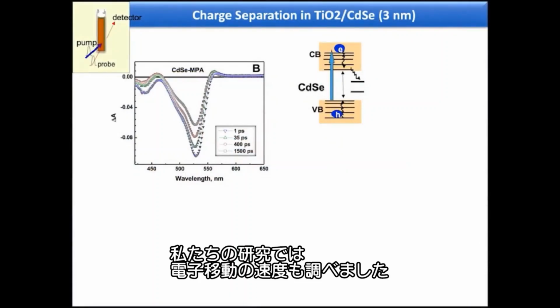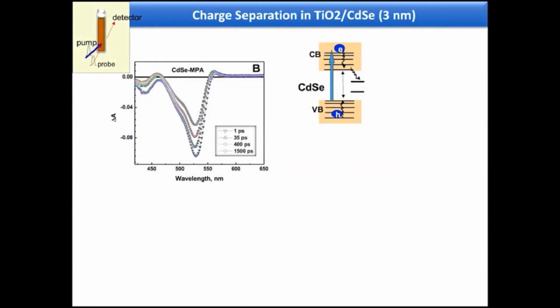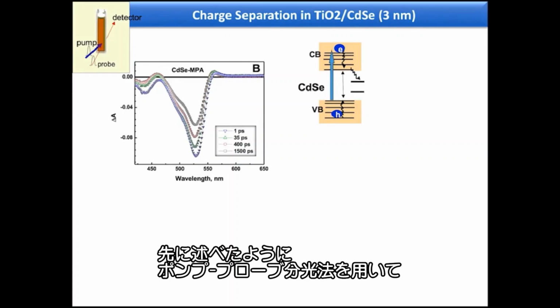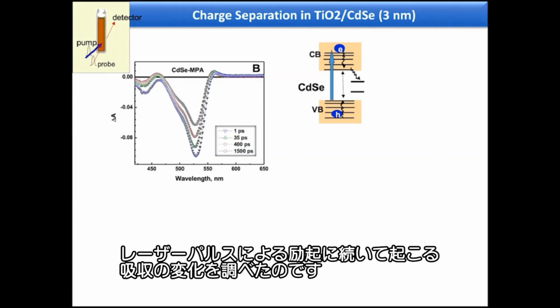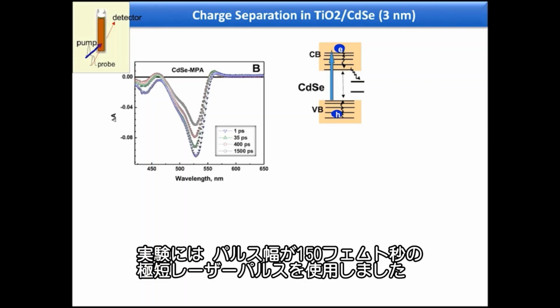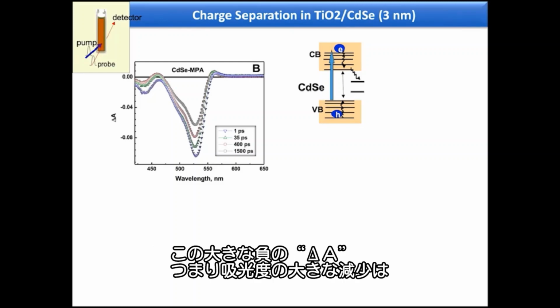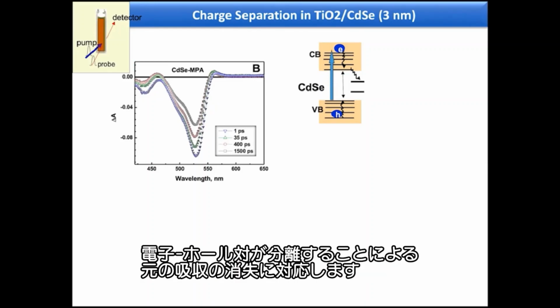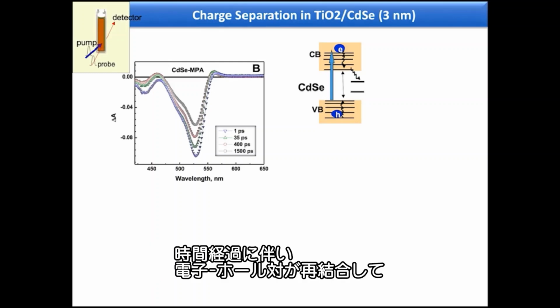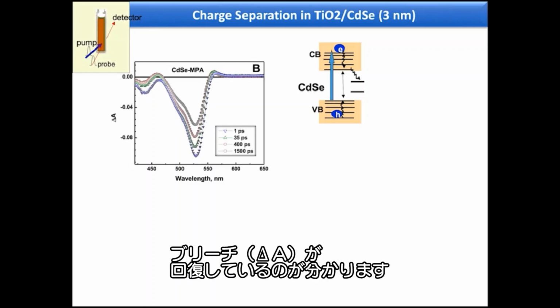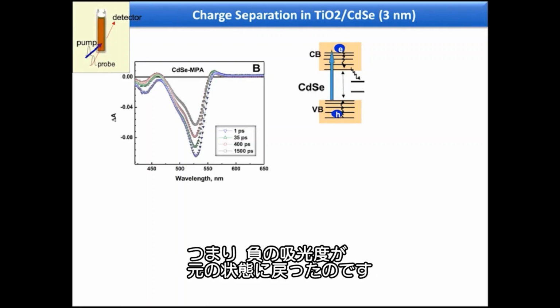Another aspect of our study was to see how fast this electron transfer occurs. As I said earlier, we use pump probe spectroscopy, which follows the absorption changes in the system following a laser pulse excitation. We use an extremely short pulse laser, which is about 150 femtoseconds, and the negative delta A, or negative delta absorbance you see, corresponds to disappearance of the original absorbance as you separate these electron hole pairs. With time, these electron hole pairs recombine, and we see a recovery of this bleach, or the negative absorbance, and it comes back to its original state.